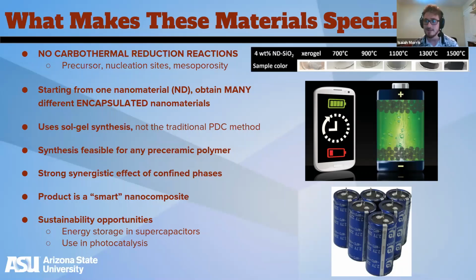You also have to consider the mesoporosity, as when a material exhibits mesoporosity, it is essentially a bunch of interconnected pathways allowing for the diffusion of carbon monoxide and silicon monoxide gases to leave the material, as well as at the same time hindering the direct silicon carbide bonds that form within the material itself, therefore suppressing those carbothermal reduction reactions. Another very important thing to note is that you can obtain many different encapsulated nanomaterials starting from one. Starting from one nanodiamond, you can thermally decompose that to obtain different nanomaterials with different properties. Like you saw the OLCs, the onion-like carbons, they behave quite differently than the typical nanodiamond.